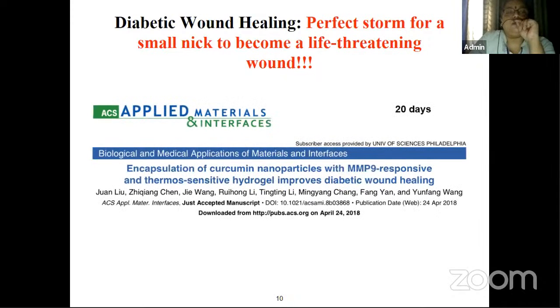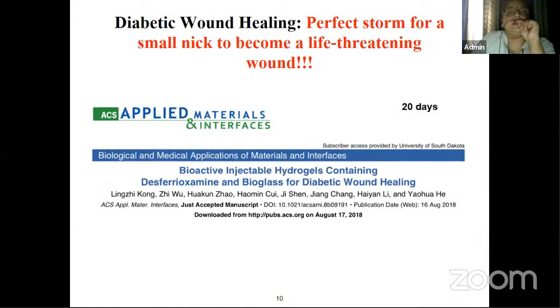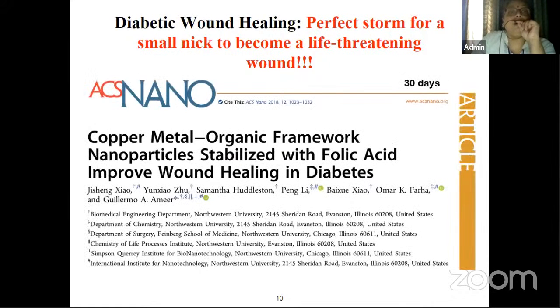When studying this in ACS Applied Materials and Interfaces, they used encapsulation of curcumin nanoparticles with thermosensitive hydrogels, which improved diabetic wound healing, but they took 20 days. Then, in ACS Applied Materials and Interfaces, bioactive injectable hydrogels containing bioglass for diabetic wound healing took 20 days. Then in ACS Nano, they came with 30 days, with copper. So again, metal is coming here. Organic framework nanoparticles stabilized with folic acid improved wound healing in diabetes.